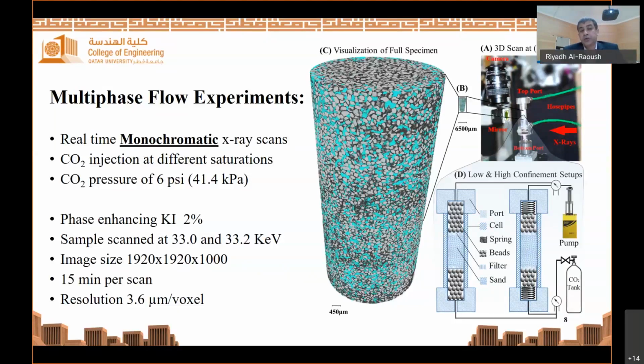Here, to enhance the contrast of the phases of the image, we doped the water by adding 2% of potassium iodide. Then the sample was scanned at 2 different energies, below and above the iodide edge. You can see here the image size is about 2000 by 2000 by 1000 voxels, and it took about 15 minutes per scan to complete the experiment. And the resolution of the image that you see here is about 3.6 micron per voxel.